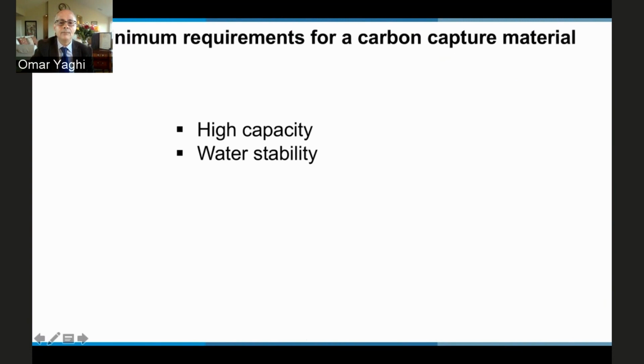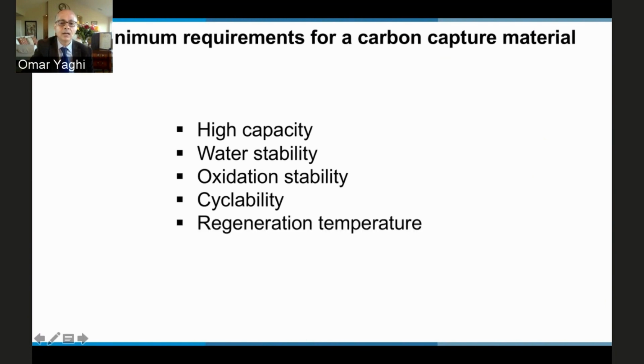So you need high capacity, you need a material that's water stable. Now you see how every atom being a surface becomes very important for high capacity. And you see how my emphasis on the strong bonds and covalent bonds becomes important when you talk about water stability, oxidation stability, cyclability, and we need to keep our eye on the regeneration temperature and make sure that that is lower, not higher, since that's energy that you have to put into the system.